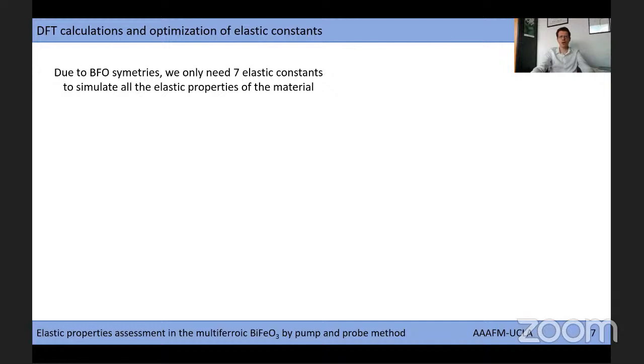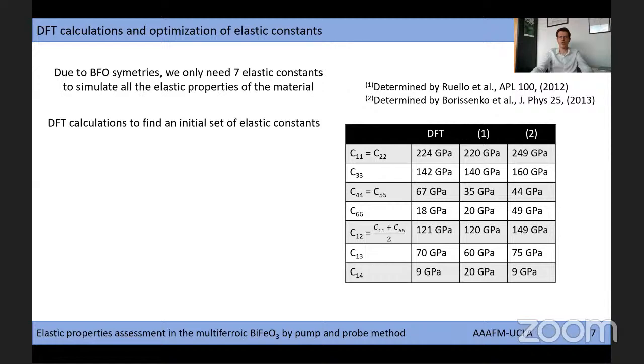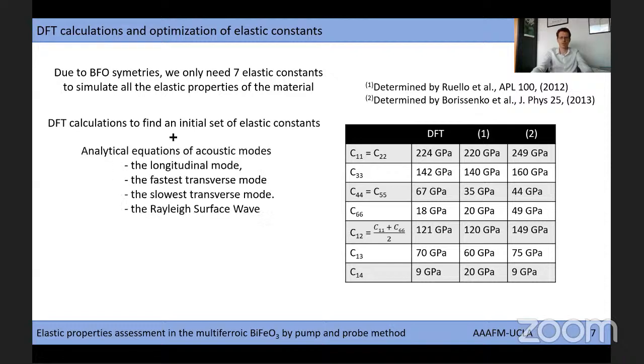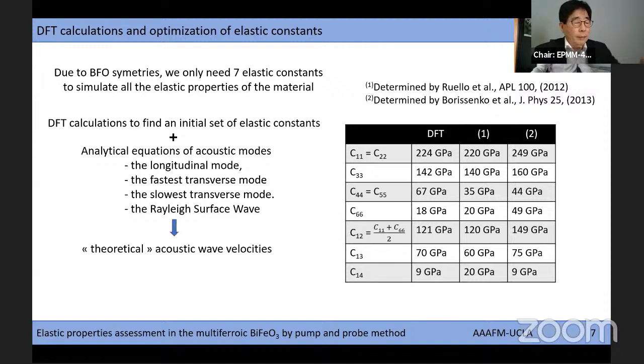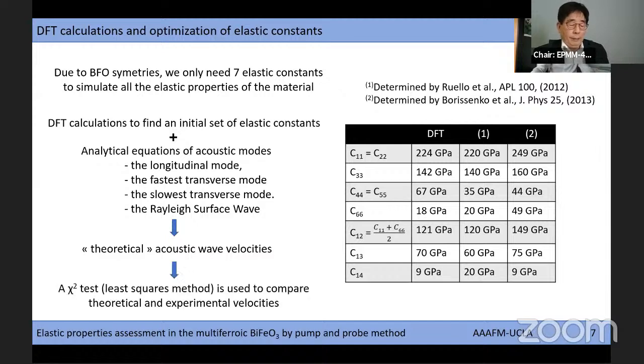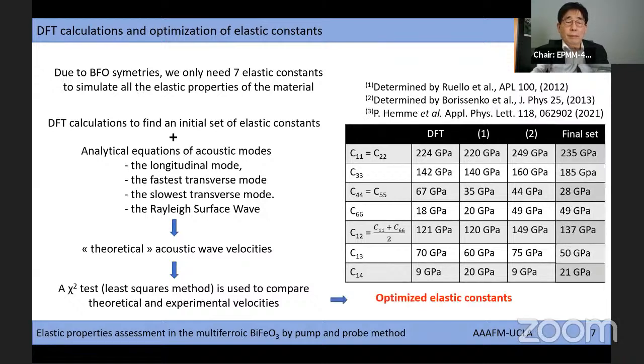Thanks to BiFeO3 symmetry, only 7 independent elastic constants have to be determined. To do that, we first calculate a set of elastic constants using DFT calculations. This set of constants is then used in the Christoffel equations of acoustic modes. We can thus determine four theoretical velocities: the longitudinal mode, the fastest transverse mode, the slowest transverse mode, and the Rayleigh surface mode. The values of the elastic constants are optimized by minimizing the difference between the experimental and theoretical velocities. Finally, we have determined all the constants of BiFeO3.